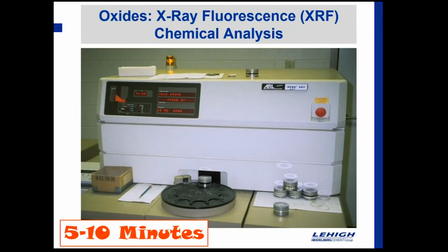And this is where we could take that same cement powder, and in about 5 or 10 minutes, we're going to be able to give you a very accurate, highly calibrated breakdown of the composition of that. So that's where your oxides are going to come from in terms of the data generation, would be X-ray fluorescence.